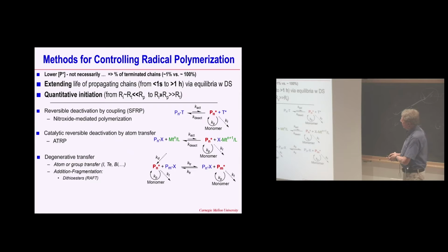Here is a different story in this equilibration process because you establish radical concentration by activation, deactivation. And because of that, you are completely independent of this termination process. Propagation is still 1,000 times faster than termination, but initiation can be even faster than propagation. So if I take an initiator which contains 5 functional groups, in a conventional radical process, I would try to make a star, but I will make one arm here, one arm there, one somewhere else. I could never make a star. In this control process, I will progressively grow all of the chains, and they will give me a star-like structure or bottle brush-like structure or bioconjugate, organic-inorganic hybrids, and some other fancy stuff.